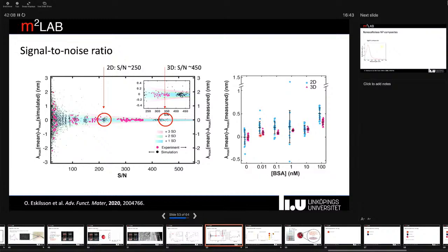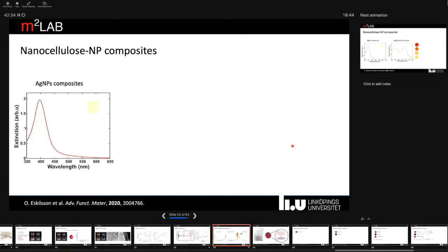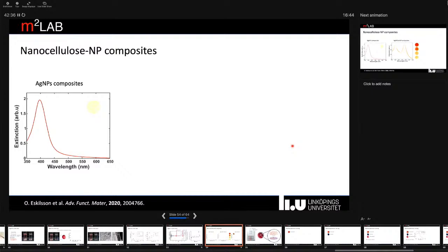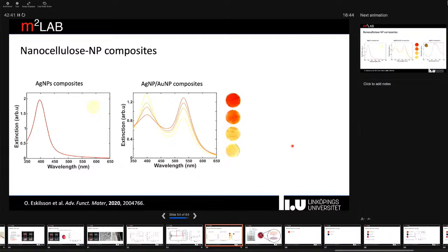And if we just look at an example here where we adsorb bovine serum albumin on the surfaces, we see that there is quite small variation in the pink three-dimensional data, whereas in the blue two-dimensional data, there are quite much larger variations due to the lower signal to noise. But this technique with the self-assembly of the particles in the membranes, we can also essentially